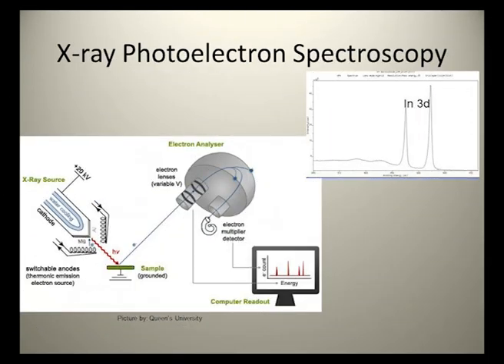I studied X-ray photoelectron spectroscopy for surface chemical analysis. In XPS, samples are loaded in ultra-high vacuum where monochromatic aluminum K-alpha X-rays are produced. On the other side of the chamber, the hemispherical electron energy analyzer is used. We can subtract the X-ray energies and electron energies to determine electron binding energies. This data helps identify elements and determine composition of the surface layer. With reference spectrographs, I was able to locate the indium 3d doublet peak from the dataset.